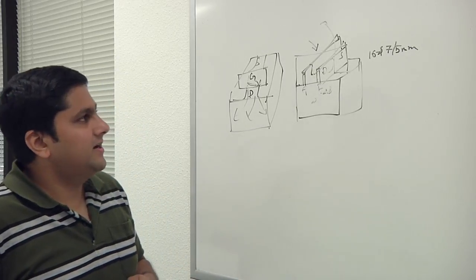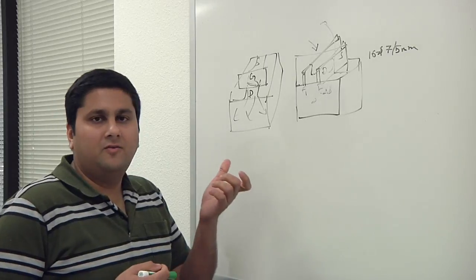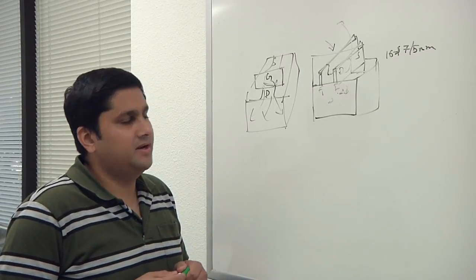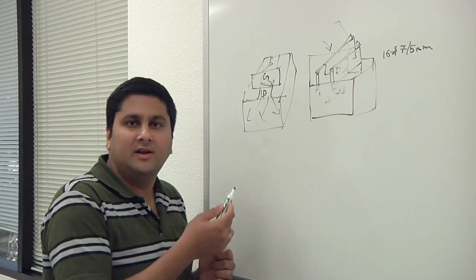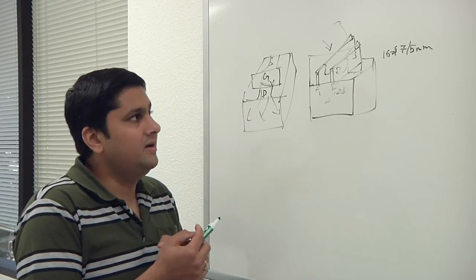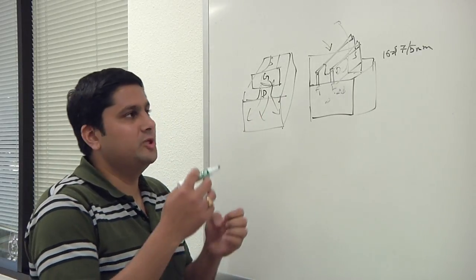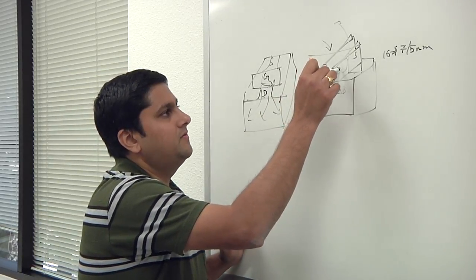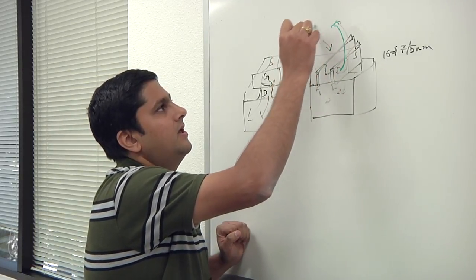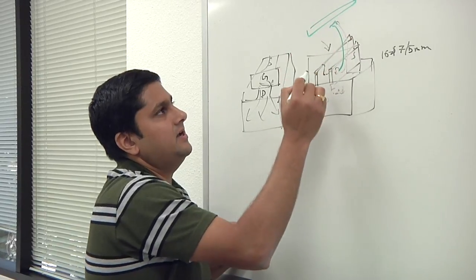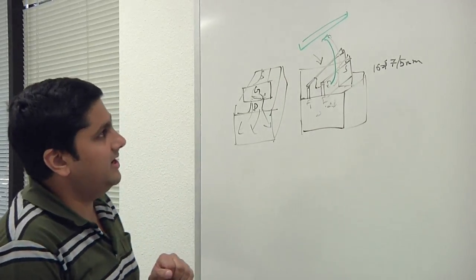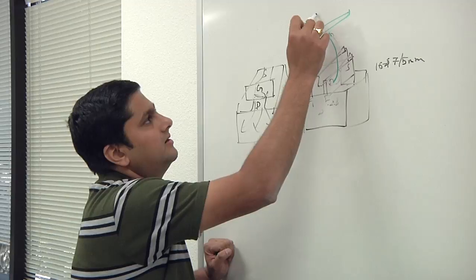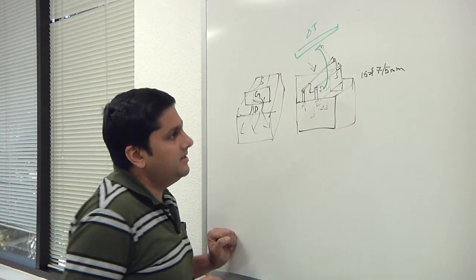So the real impact is on your back end of the line interconnects. Basically, you have thinner interconnects which carry more amount of current. You have 3D devices which cannot dissipate the heat through the substrate. So your heat gets coupled from the device to the interconnect, and your thinner interconnects, basically carrying higher amount of current, lead to higher delta T or joule heating on the interconnect.